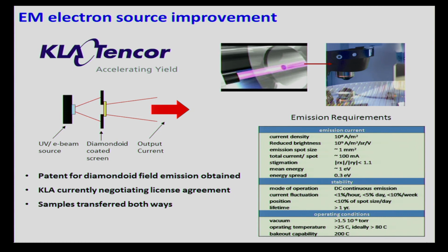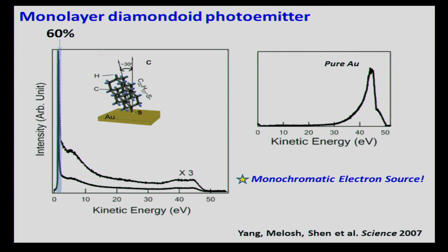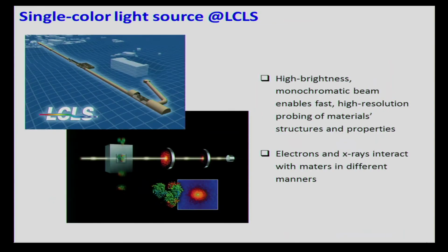The only thing that has been stopping us from putting it to real use is the lifetime. You can imagine that because this is only a single molecule, a monolayer of molecules bound on the surface by a single atom, this is really, really unstable, especially when you operate it by bombarding it with a lot of photons and having a lot of electrons coming out of it. So eventually they just fly off the surface, and when they fly off the surface, this sharp peak disappears.